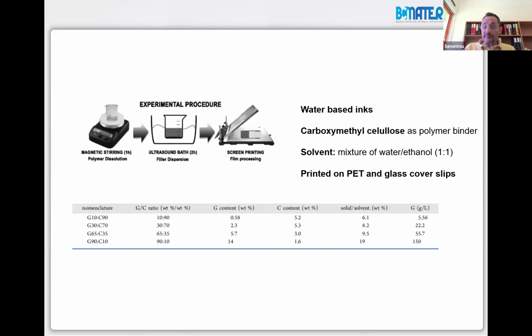We can go even further. We can choose the best of the solvents that we have, of the functional materials that I have: one of the graphenes, reduced graphene oxide, and we use carboxymethyl cellulose, a fully green polymer binder, and a mixture of water and ethanol for improving the printability, adhesion, and solvent evaporation. And then I prepare different solutions from 10% to 90% graphene cellulose content, to the opposite, 90 to 10.